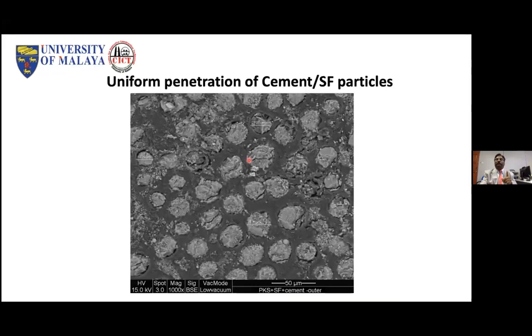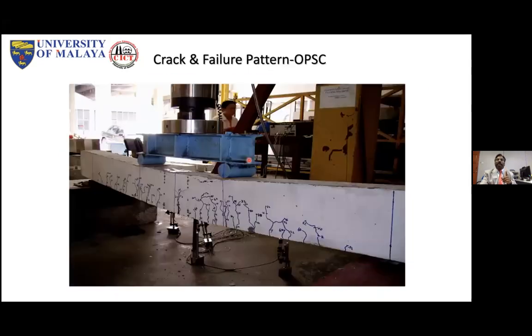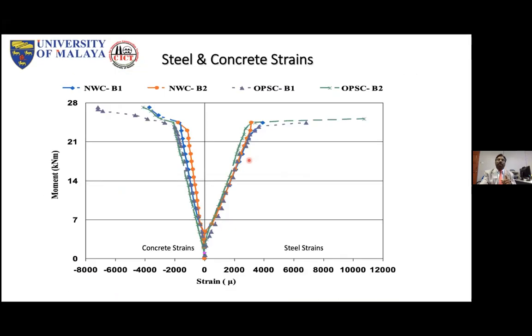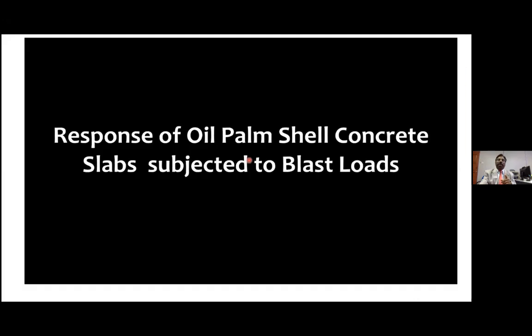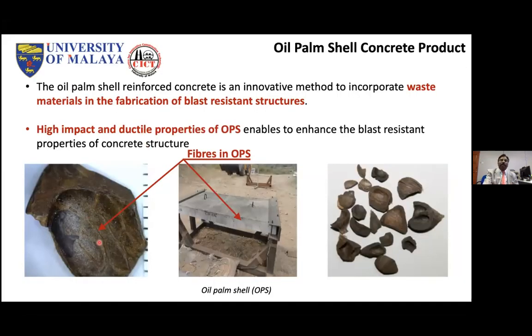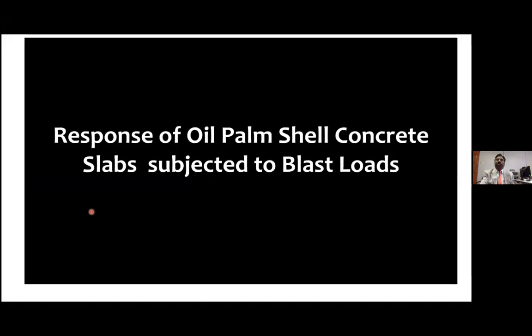This is number one. Number two is when these surfaces I mentioned here, you have seen it in the blast. See here, it's fibrous, a lot of fibers, they act as a fiber. So this fibrous characteristic of this OPS enables them to withstand, not to crush, not to crumble, but it absorbs the energy. So this is what we identified in this one.